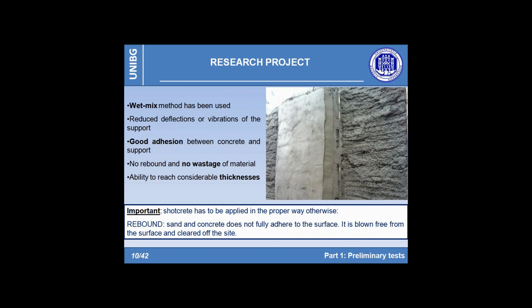Moreover, the success of the preliminary test has been also reached thanks to the efficiency of the selected EPS panels, both in terms of roughness and of number of panel stiffeners. All these features have permitted to obtain a considerable thickness, in particular more than 20 centimeters, without wastage of material and permitting to progress with the experimental campaign.